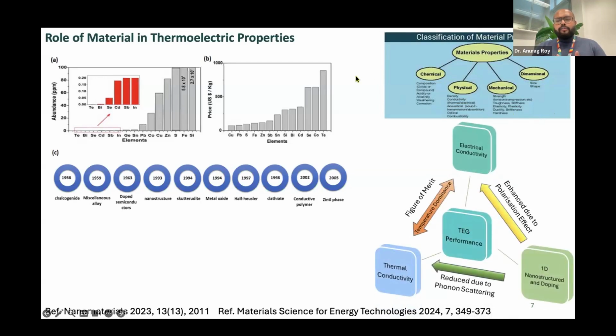And once we deal with the material, here is a very important thing: the TEG performance depends majorly on these 3 parameters: electrical conductivity, thermal conductivity, and of course nanostructures and doping. And these all 3 are interrelated to each other, and there is a trade-off at the same time. In the case of electrical conductivity and thermal conductivity, there is a temperature dominance zone. So they actually control the figure of merit, which is a parameter to determine the thermoelectric efficiency.